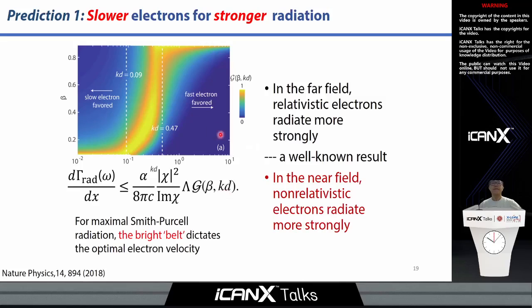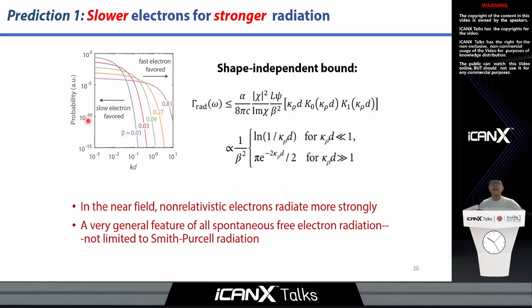If you're in the far field where kd is large, relativistic electrons are optimum to generate stronger radiation. But as your separation gets smaller and smaller, slow electrons get favored. This regime is quite interesting, and quite counterintuitive too. In fact, this characteristic is not limited to Smith-Purcell radiation. If we go back to the shape-independent upper limit, we find that this dichotomy of the radiation regimes is still there. The reason for this dichotomy is the different asymptotic limits of our upper limit towards either near field or far field.